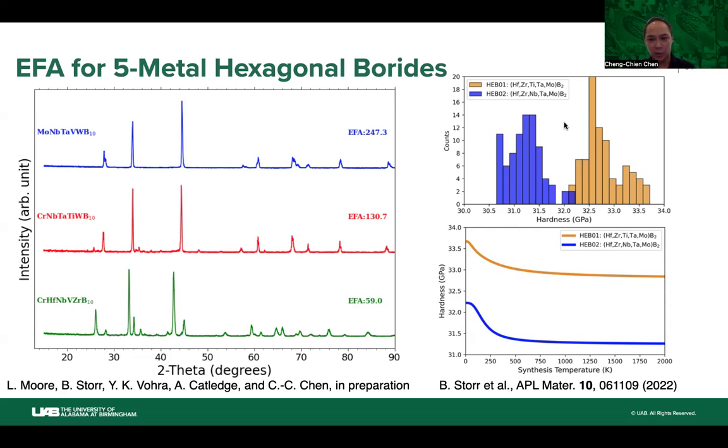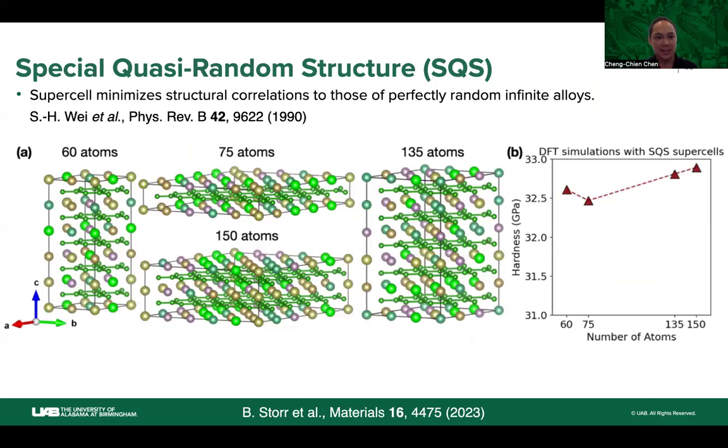However, there are two drawbacks. First of all, you need to consider all possible structures, which is not very convenient. It would be nice if we could get the results in only one single calculation. And second, here we have a minimum of only one transition metal per unit cell for a specific kind of element, so we cannot discuss, for example, lattice mismatch effects or clustering or short range correlation between different transition metals.